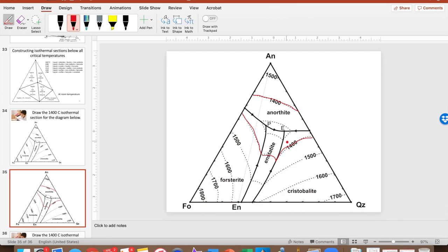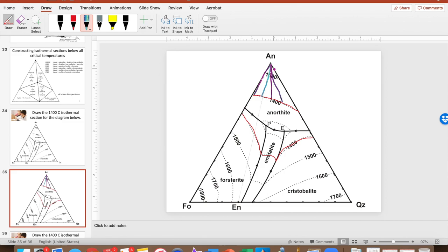Everything outside, we're going to look at our connections to the solid phase. Starting with the AN phase here — this is a terminal phase so its composition is at the corner of the phase diagram. We draw tie lines from that composition to the liquidus, reaching the ends of these boundaries. So this whole region is going to be liquid plus the AN phase.